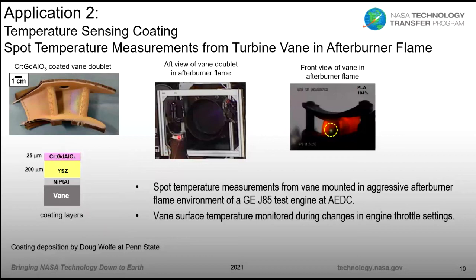We then mounted our vane in the back of an afterburner flame. That's a GE J85 test engine at Arnold Engineering in Tennessee. And then I can show you, we can ramp up that afterburner throttle setting. And you'll see the flame getting stronger and stronger. And that's heating up the side of the vane that's facing the flame. If you take a photograph from the other side of the vane, you can see how that vane is glowing hot. And right here, that's the laser spot. So that's where we're collecting our temperature measurements from. Then the idea was to measure the temperature of this spot as we throttled up that afterburner power.